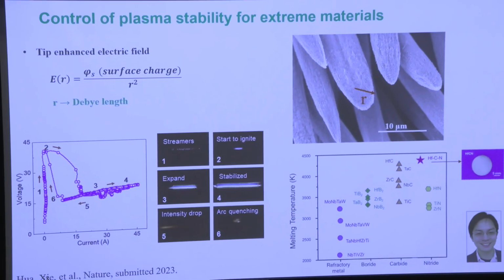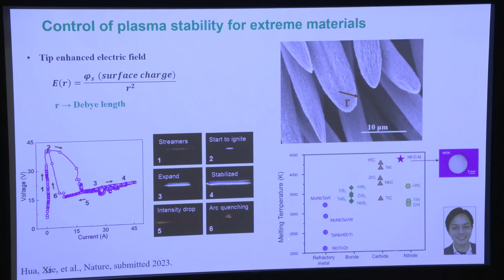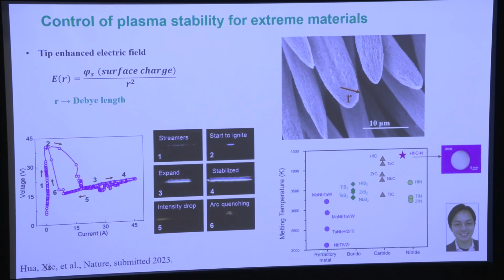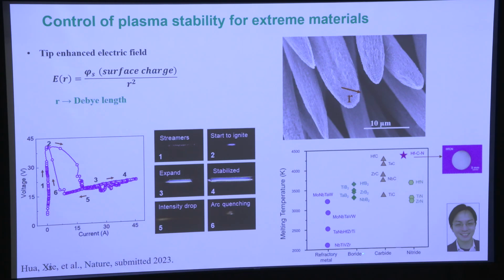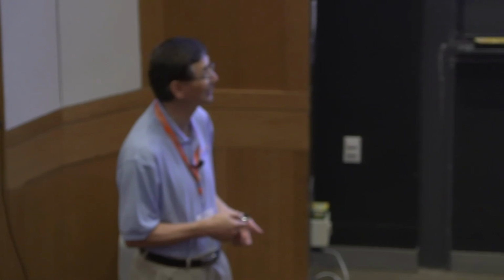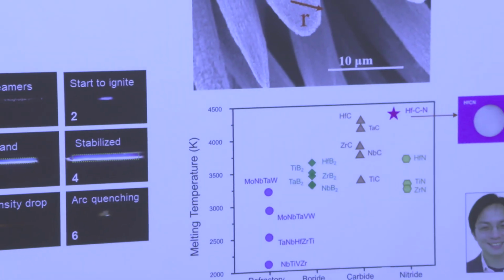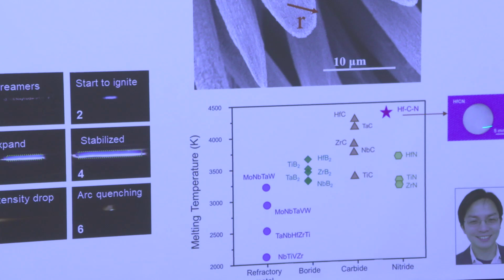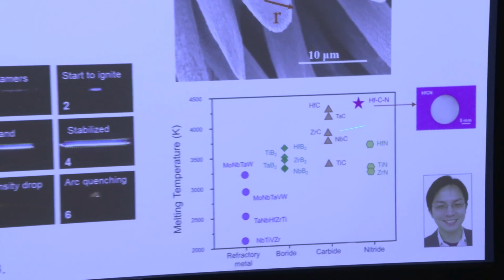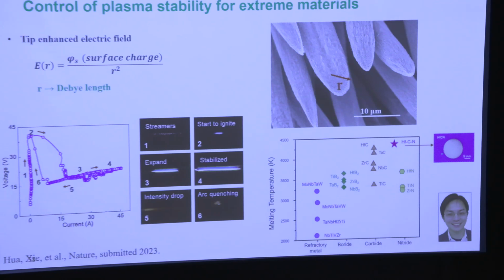I'll show you a material that we can make. He's a materials person, and he tells me that this is the melting point of materials, and these are different materials: carbide, nitride, and boride. One of the targets is hafnium carbon nitride. People computed this structure using quantum chemistry, and they say that this has the highest melting point. But people can make it using spark, making nanoparticles, but no one can make it in bulk. If we have a bulk plasma like this, we can make bulk materials.